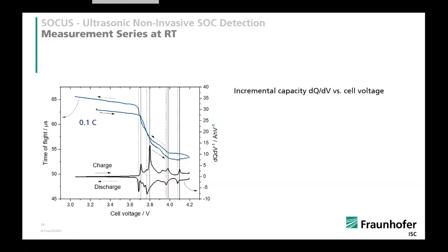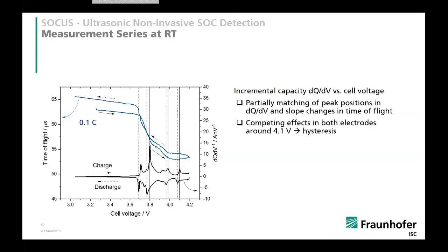And a different type of graph, the very same time of flight, this time not over the cell capacity, but over the cell voltage on the left side, and the incremental capacity dQ over dV for the electrochemical data. And what you actually see is that for the distinctive peaks that are highlighted by the vertical lines, there's a match of the time of flight data with these peaks. And around 4.1 volt, you have quite a substantial hysteresis of the time of flight curve. We think that this is due to a competing effect on the anode and the cathode side.